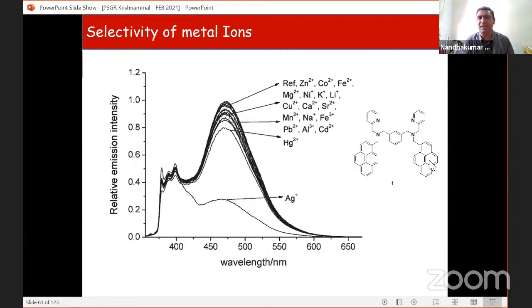That means these two pyrenes come close together. So in the excited state, they form a dimer, these together. This is one, this is two. They come together to form a dimer. So this is a dimeric species, and that's what we call the excimer peak. So this is the excimer peak, and this is the monomer peak. So what happens is the monomer increases and is enhanced, and the excimer quenches in this case.